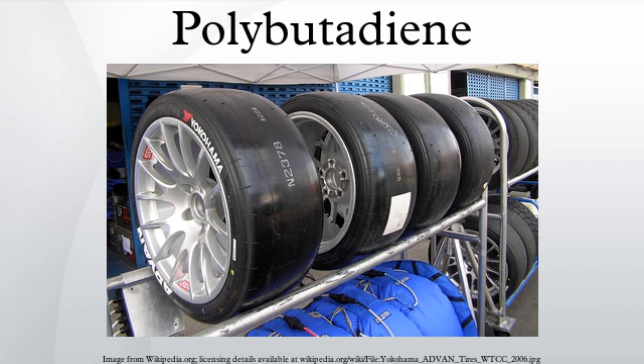In 1980, researchers from the Japanese company JSR discovered that high-vinyl polybutadiene, despite having a high glass transition temperature, could be advantageously used in combination with high-cis polybutadiene. This material is produced with an organolithium catalyst. In addition to JSR, the American company Firestone produces high-vinyl polybutadiene. JSR Corporation markets a type of polybutadiene with 90% vinyl, giving it the properties of an elastomeric thermoplastic — elastic at room temperature but a fluid at high temperatures — which makes it possible to process it using injection molding.